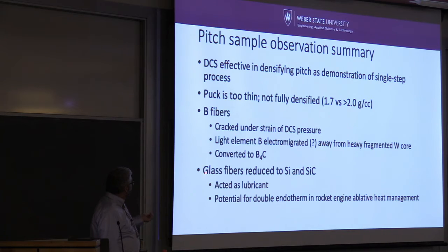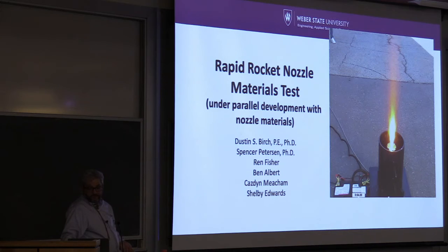Boron fibers cracked, glass fibers reduced. And by the way, that's kind of cool because the glass fibers melted and then they reduced. And what does that mean for the ablative thing that I talked about? That's a double endotherm. You can talk about two sources of pulling in heat to the material before you blast it out the nozzles. So that's a potential aspect for an ablative material. Okay, so very quickly, when do we tie it up?